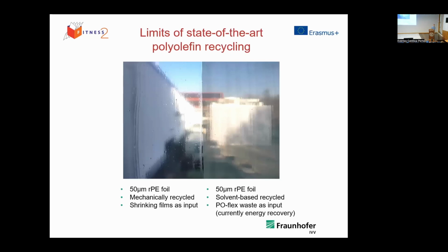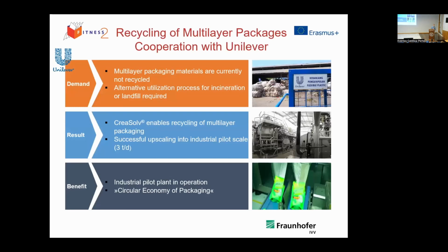And now I come to a few projects which we have currently running. One is the cooperation with Unilever, which tackles the problem that multi-layer packagings can currently not be recycled, and an alternative for landfill or incineration was necessary. And we have proven that the recycling of these multi-layers is feasible with the CreaSolv process, and we've already successfully upscaled it into an industrial pilot scale with a capacity of about 3 tons per day. This pilot plant is already in operation for, I think, about 2 to 3 years now. And it proves a circular economy of packaging materials because the recyclates from this plant are already reused in new sachets in Southeast Asia.